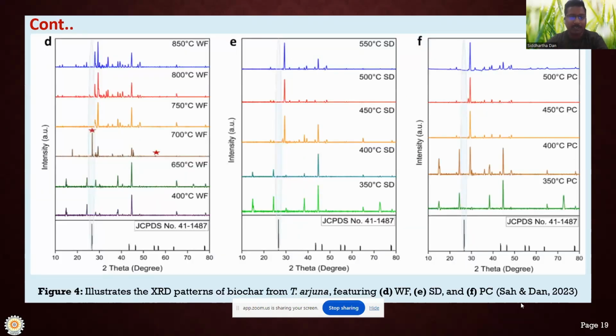The temperature range is only 400, and the next 650 to 850. The powder XRD crystallography analysis of the synthesized biochar revealed its crystalline nature. In graphite obtained from whole fruit, distinct diffraction peaks, that is 14.89 and 17.23, we can see with the star mark in the first graph, derived from whole fruit at 700 degrees Celsius. This is the best result in our study, and 29.30 degrees 2 theta confirms the crystalline nature, while a peak at 64.98 suggests an amorphous phase, but the peak is very small, and we can check only the main phase, the main peak.